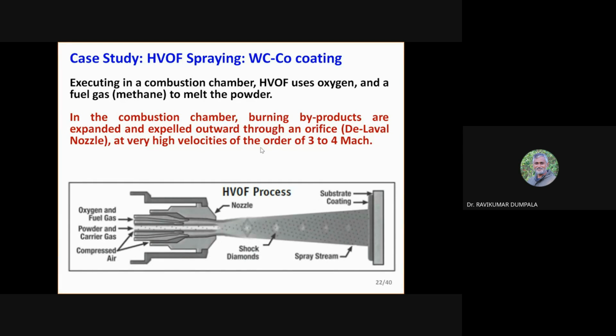But to make some material stick, some energy is required. So this process was coined in 1922 or sometime. They understood that some energy can be given as kinetic energy along with the thermal energy, so you minimize the thermal energy and increase the kinetic energy. That's what they did in this HVOF process. The temperature to which the particle is exposed is around 2000 degrees centigrade, not melting the particle, because to melt any of these materials you need 3000, 4000 degrees centigrade. So you just reduce the temperature, but velocity gives so much kinetic energy.